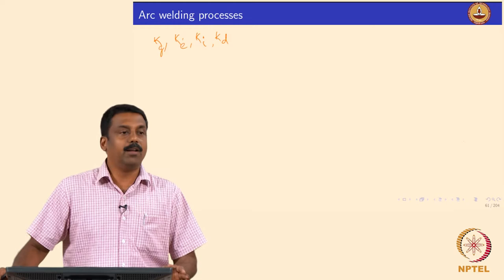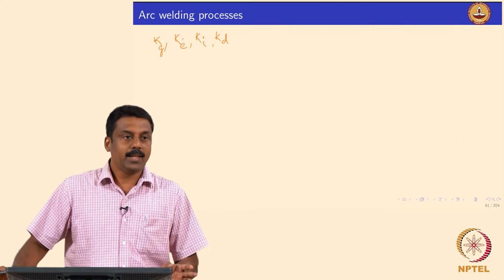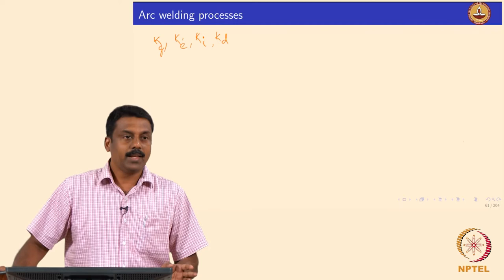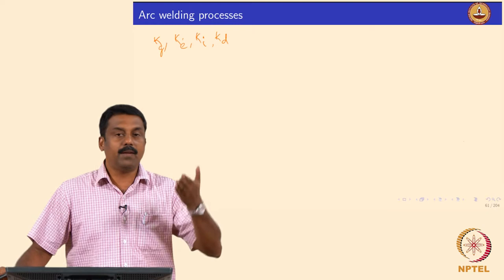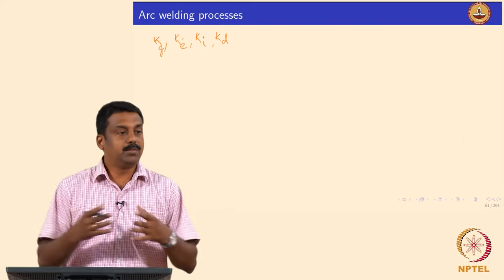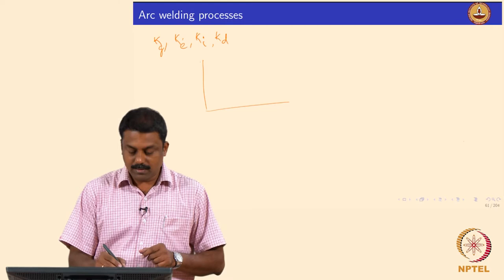Kg, Ke, Ki, and Kd — all four together determine the conduction heat transfer in the arc. We also looked at how changing from a monoatomic gas to a diatomic gas affects arc temperature. If you use a diatomic gas, you have a shouldering effect because the heat is effectively transferred and distributed throughout the volume. Looking from the arc center to the arc envelope, you will observe this shouldering effect.